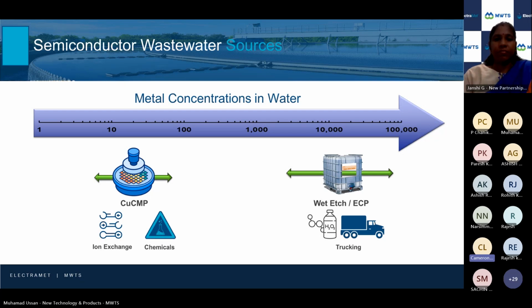So these more bulk removal processes tend to be much, much higher concentration, but lower volume. And they also contain a lot of hydrogen peroxide. So the combination of hydrogen peroxide plus the high concentrations of the metals makes it very challenging to treat on site. And so they typically just truck it off. So now there's very expensive trucking costs and very unsustainable environmental impacts from the trucking process.